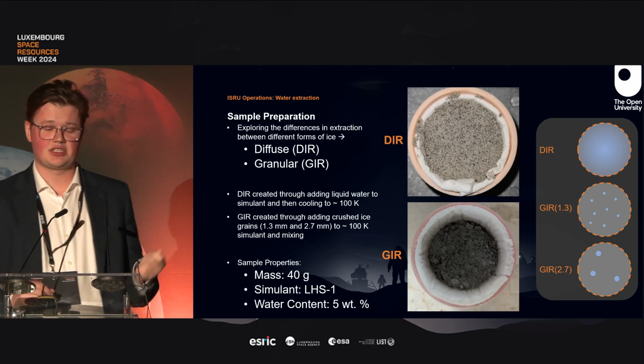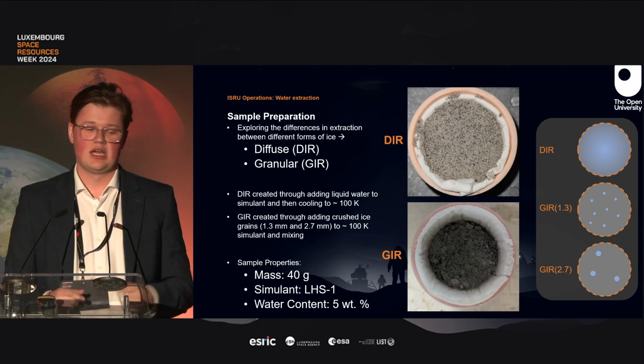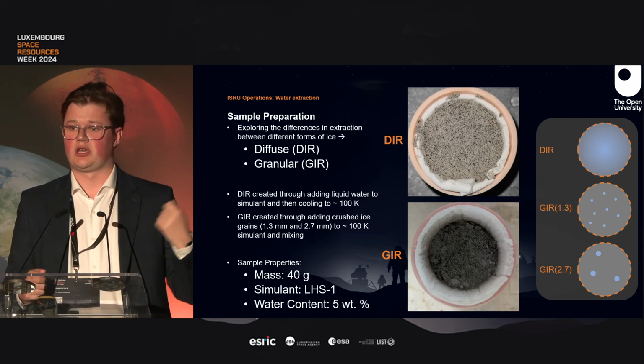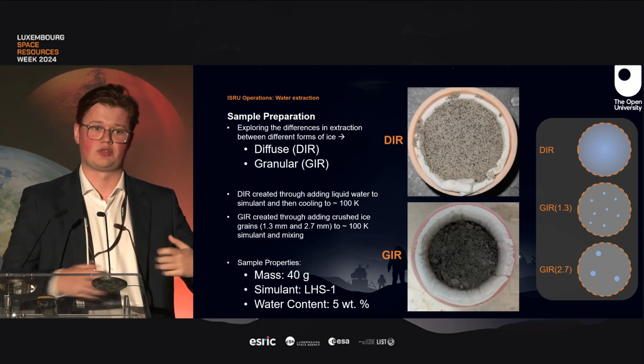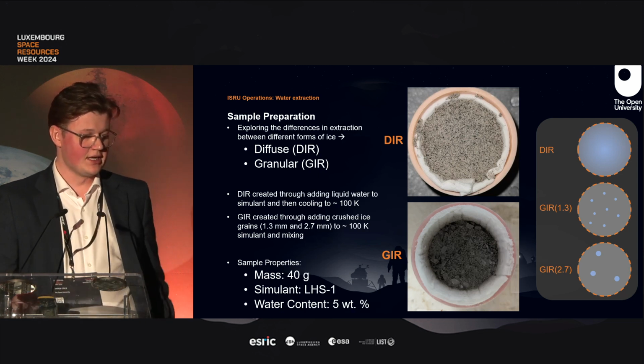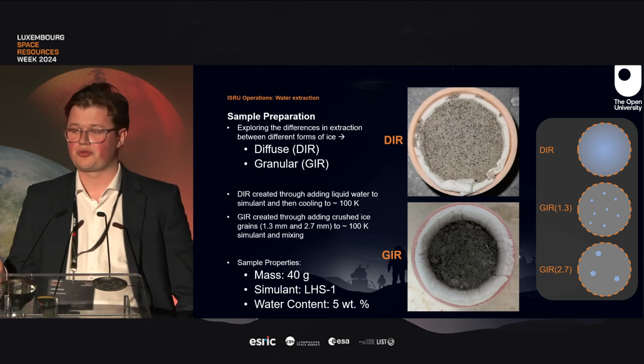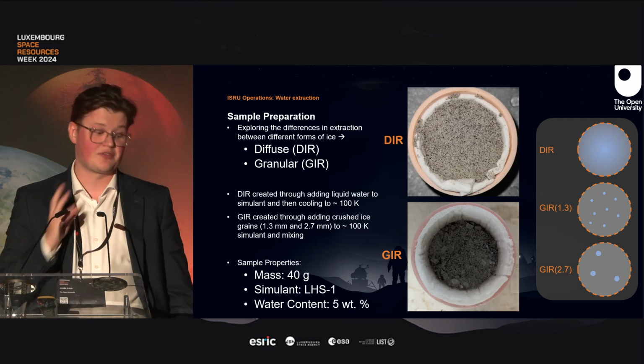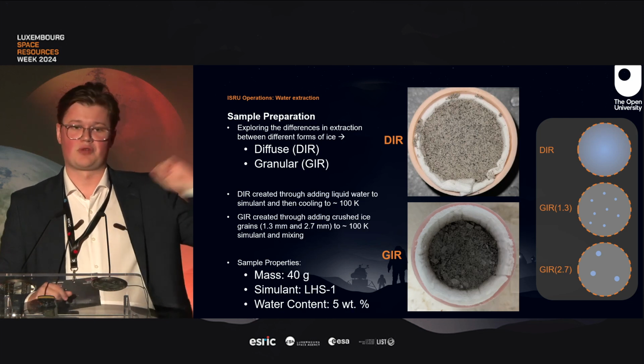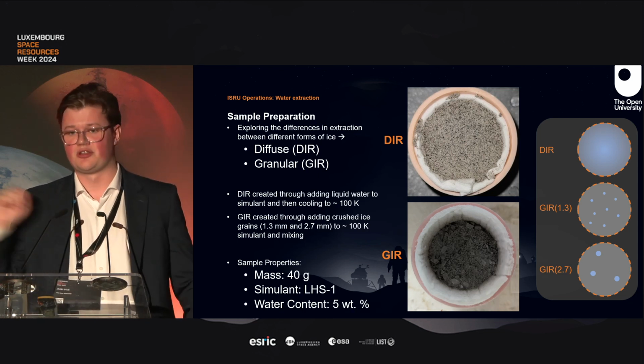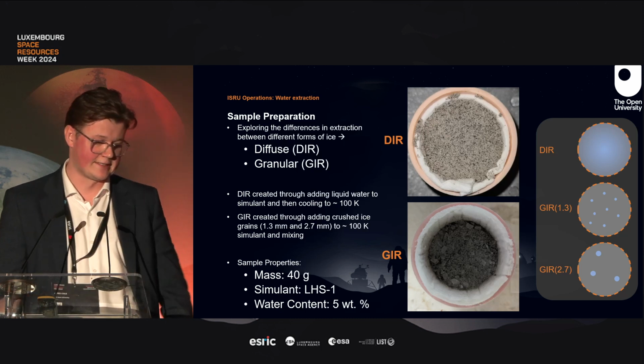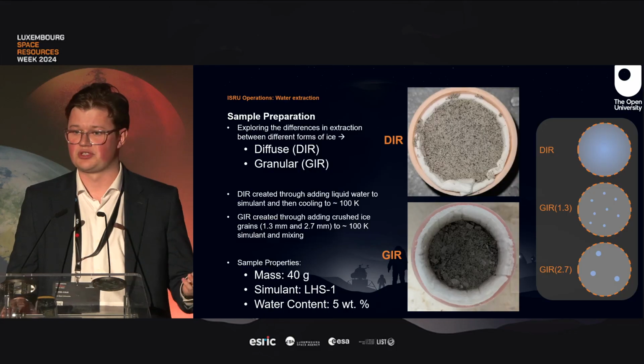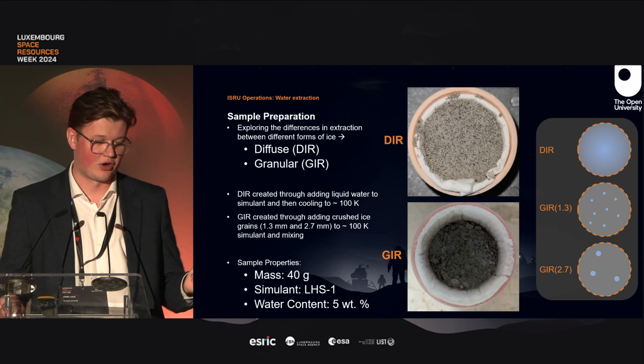So what I changed this time is I also formed some granular ice, where I add ice particles to cold simulant, and then I cool it down further to 100 Kelvin. The grains were between 1.3 millimeters and 2.7 millimeters. So as in, we had one sample type with 1.3 millimeter grains and another sample type with 2.7 millimeter grains. Apart from that, all the samples were kept the same. So they had a sample mass of 40 grams. They used LHS1 as the simulant, and we aimed for a water content of 5 weight %.